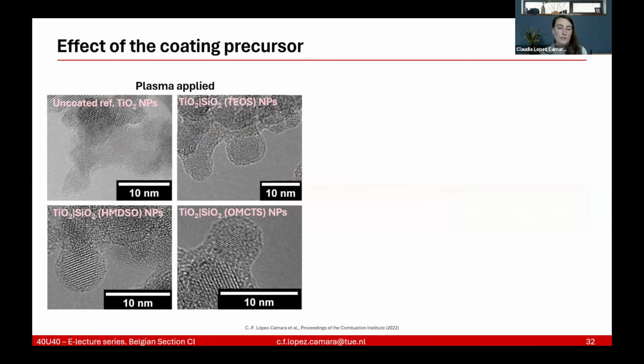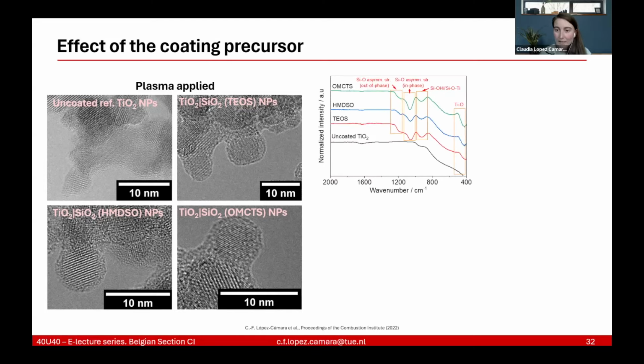So we were looking into this, and the first thing that we wanted to know is if the titanium dioxide is nicely homogeneously coated. And we saw that in all 3 cases, TEOS, HMDSO, and OMCTS, we do get this homogeneous coating. You can see from the pictures that the titanium dioxide is this crystalline nanoparticle that has all these, let's say, zebra patterns. It's not really appropriate, but just to understand each other. So this nanoparticle is surrounded by this other coated material that is amorphous. So, okay, the nanoparticle is coated homogeneously, but is it coated with silica? We did an FTIR, and we saw that the amorphous material surrounding these nanoparticles was indeed silica. So that was good news.